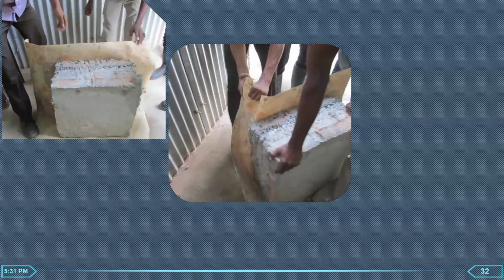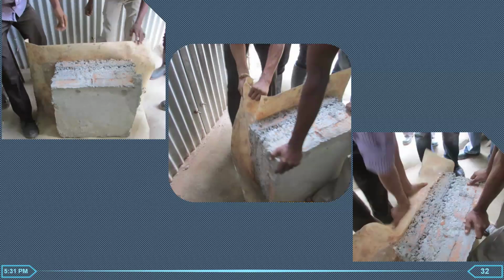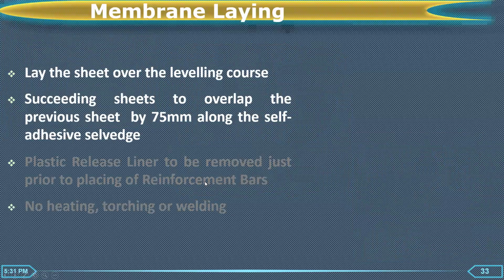No testing parameters were available at that time, maybe a few years back. So we, out of our own interest, made a cube over the sheet. And after curing and hardening, we tried to detach the sheet. Certainly, at least manually, it was not possible to detach it, showing that there is enough bonding between the concrete and the sheet, so that the horizontal transmission of the water could be avoided.